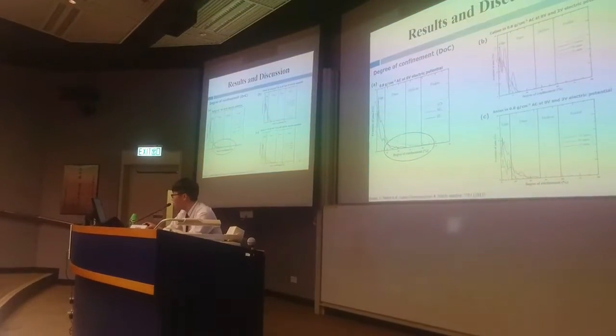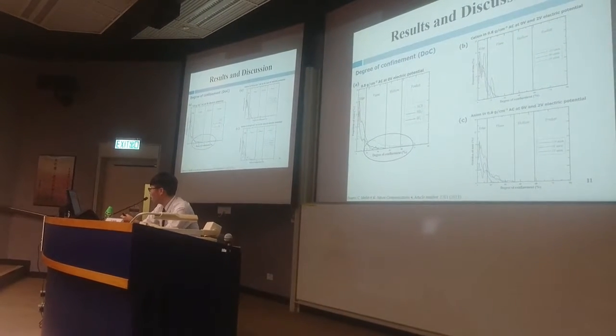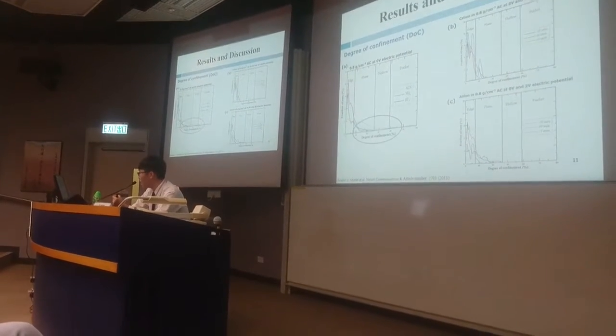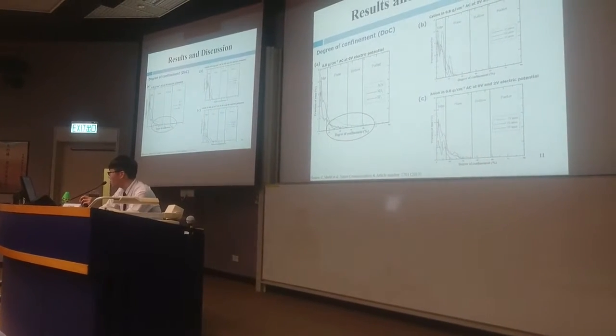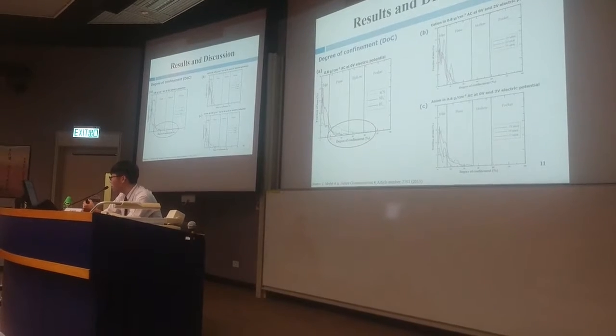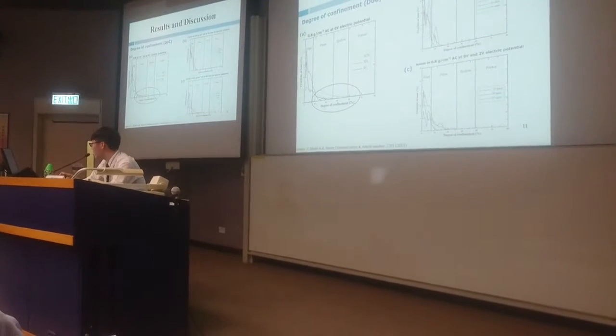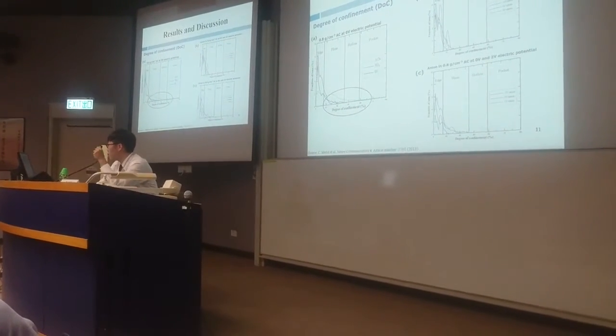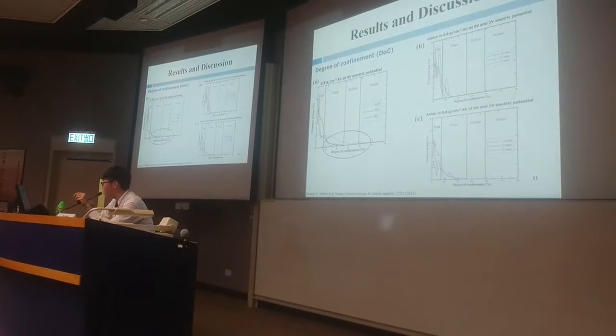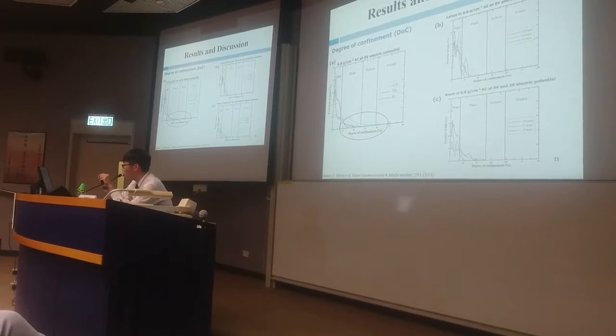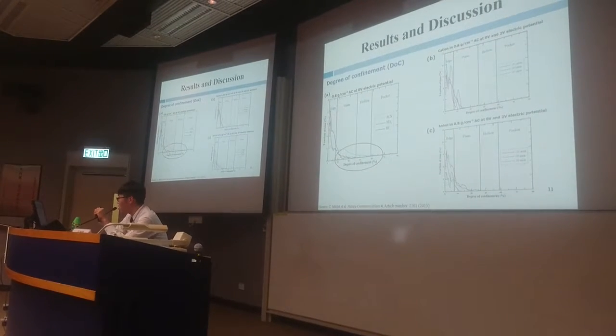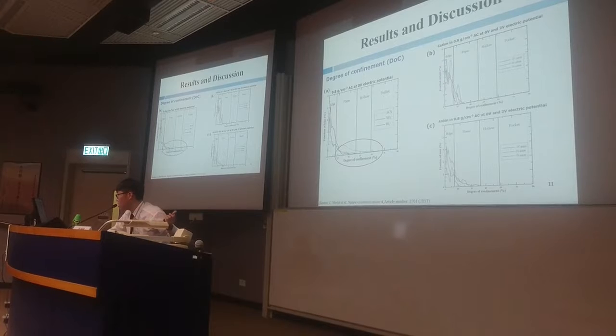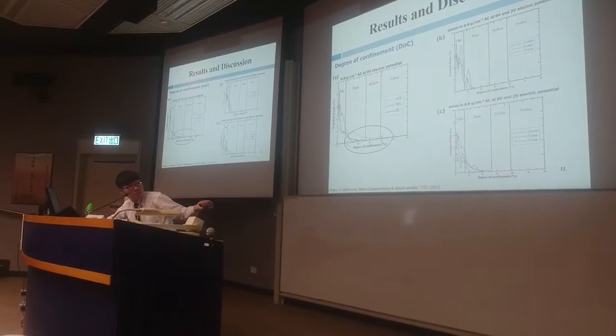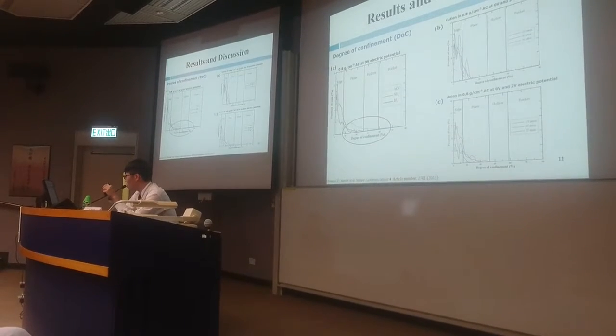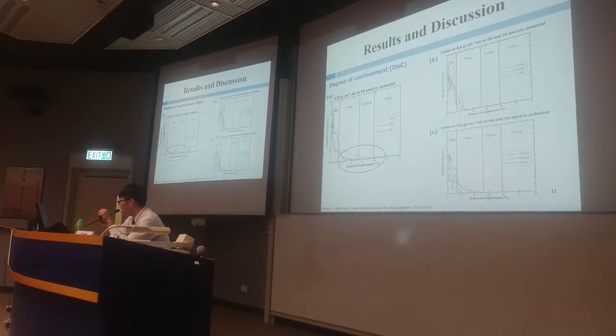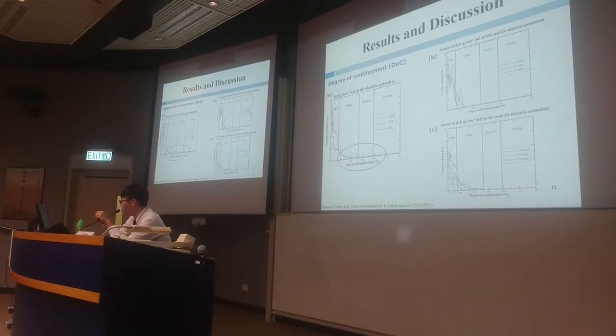In figures B and C, the cations and anions are shown in the density 0.8 g/cm³ at 0 V and 2 V electric potential. So in the cathode, the cations have a high distribution at the plane part, but are still minimally distributed in the edge parts. That's due to the large size of the cations. But the DOC of anions approaches 30%. That's due to the smaller size, so they easily diffuse into the electrodes.